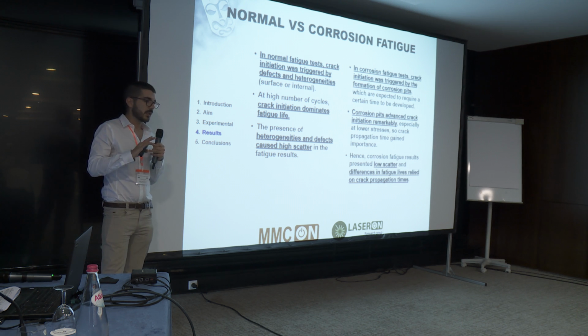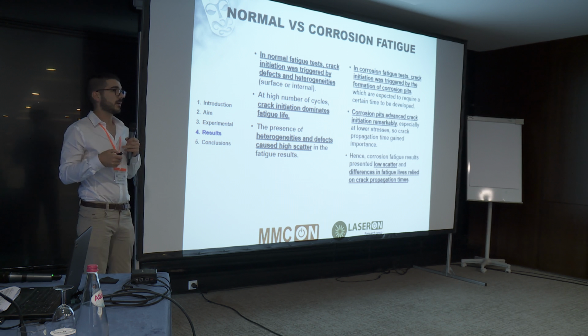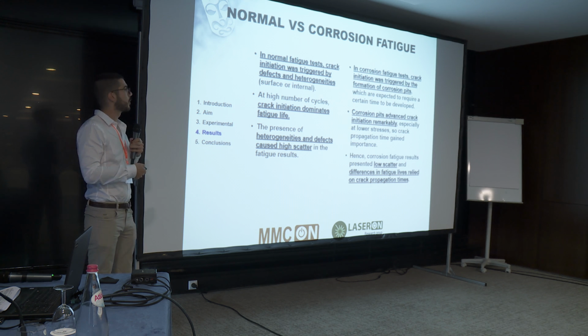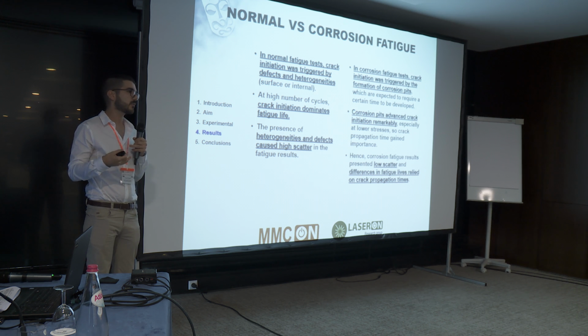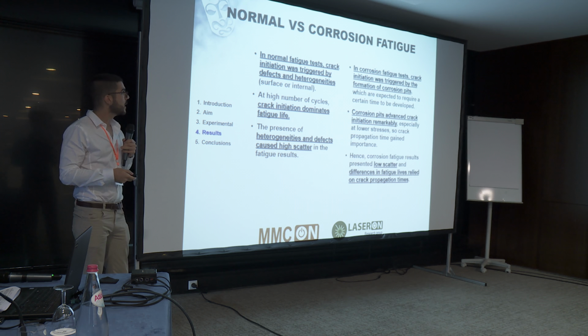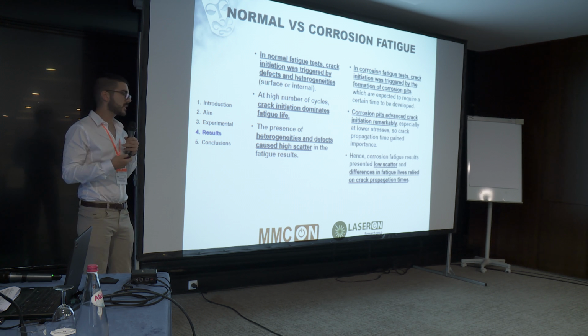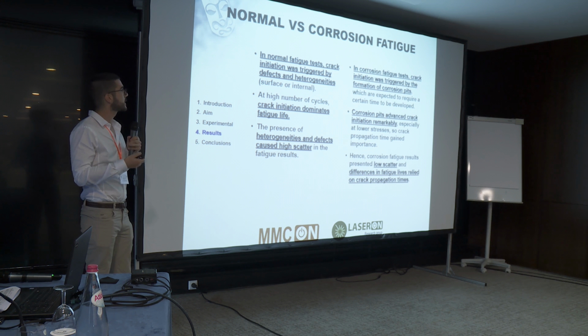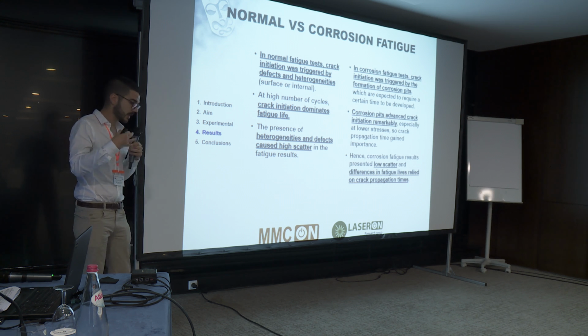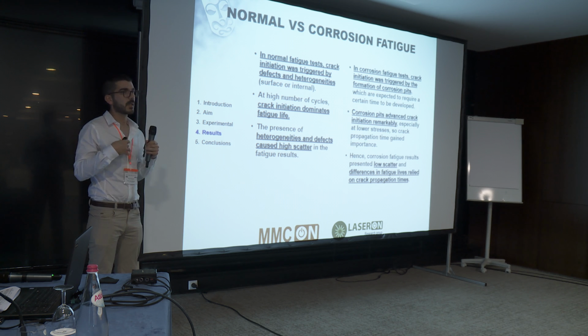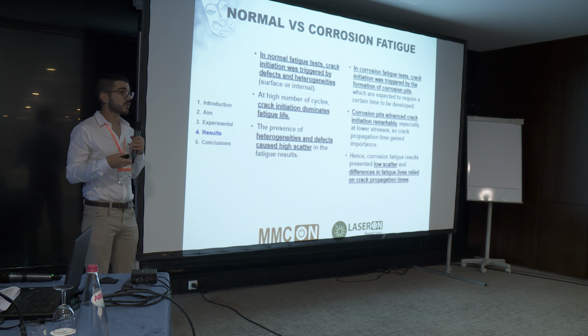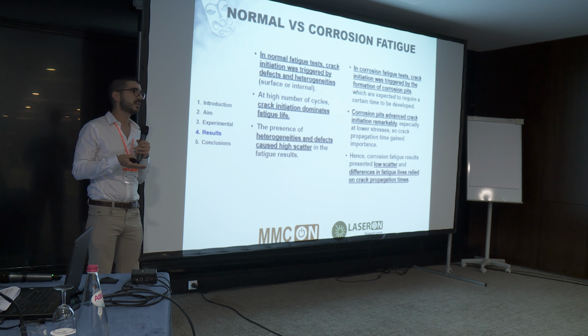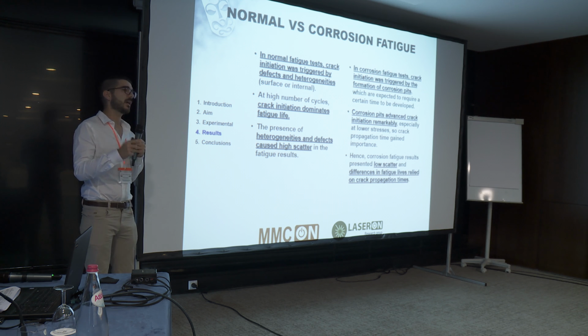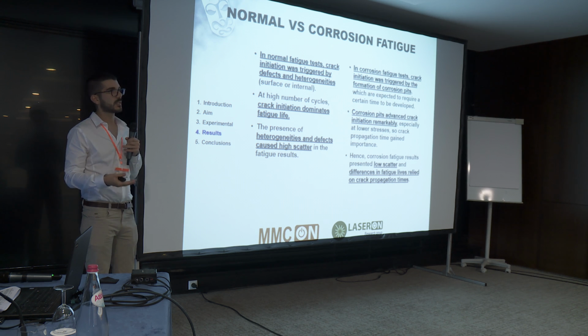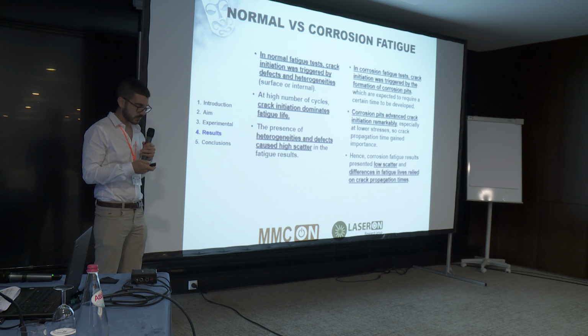So to sum up these results, as you probably already know, crack initiation at a high number of cycles dominates fatigue life results. So it makes sense that the presence of defects and heterogeneities in the steels led to higher data scatter, whereas in corrosion fatigue tests we are inducing crack initiation, and so crack propagation times gain more importance in the results, and that's why we think we got less scatter in the results.